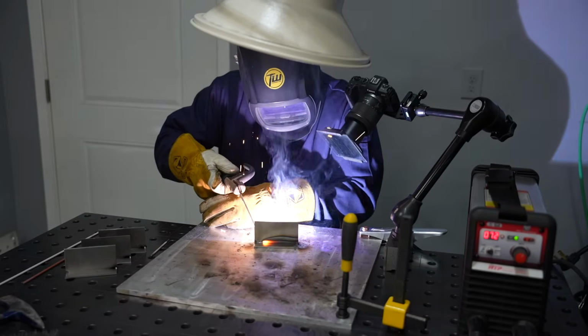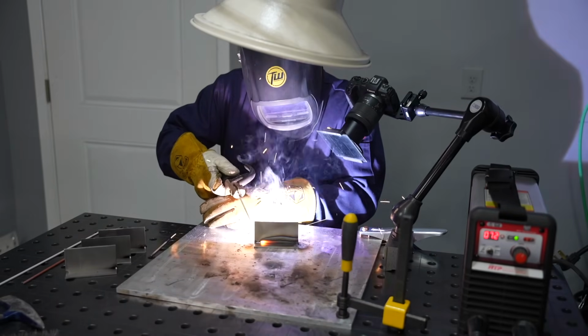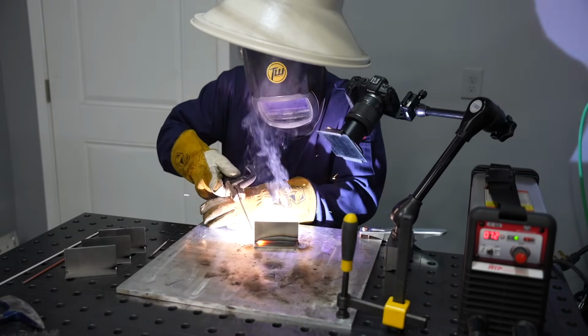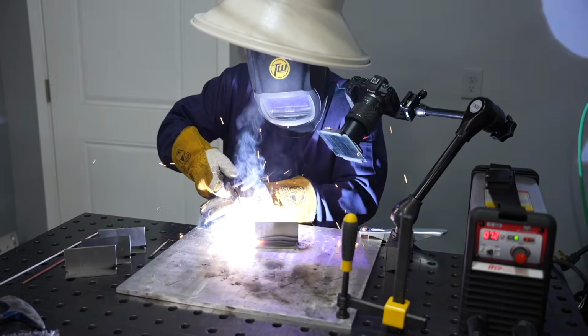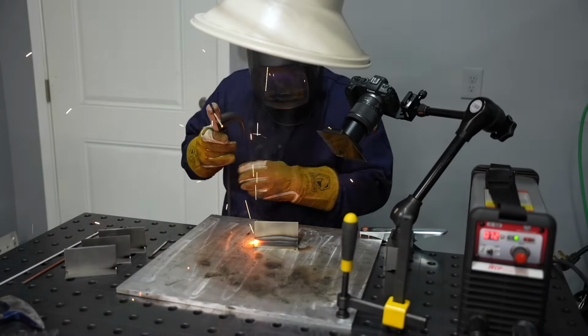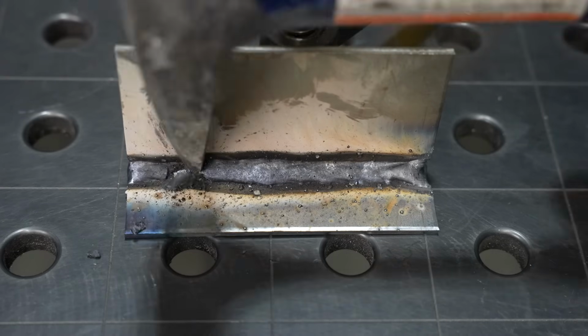Watch what happens here towards the end of the weld. I made a mistake, but I left it in there because I thought it might be good to talk about. Notice the arc length is getting long, and my angle's getting out of whack. It's a little hard to see that in this shot, but it is. The reason for that is that I had to use more electrode than I'd planned on, and my hands collapsed all the way down, that left hand that was supporting my electrode, and so I ended up getting pushed out of position.